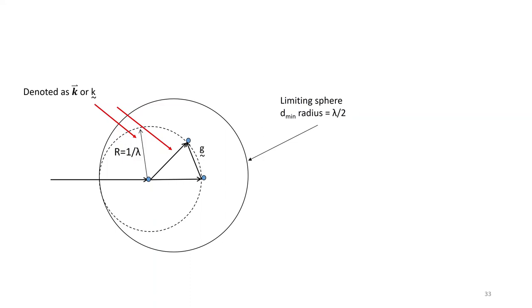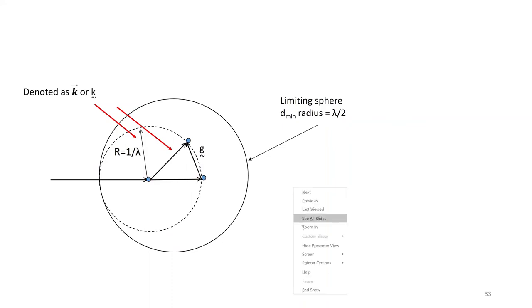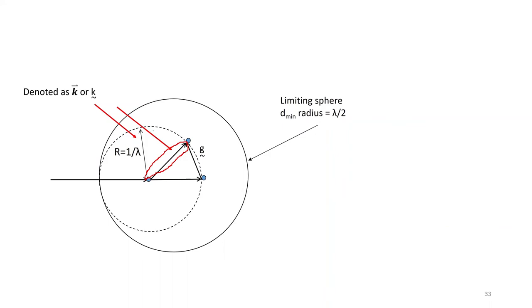Moving the sample changes which dots interact with the Ewald sphere. This is how a rotating crystal experiment works — you spin the crystal on an axis and use photographic paper. Moving the source or detector is the third manipulation method, but you really can't do that on a TEM — the column and recording plane are static. This is actually what happens when you run an XRD: you move the source and detector. Each colored circle in the depiction represents one position condition.